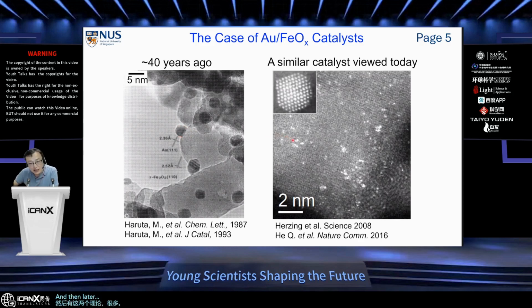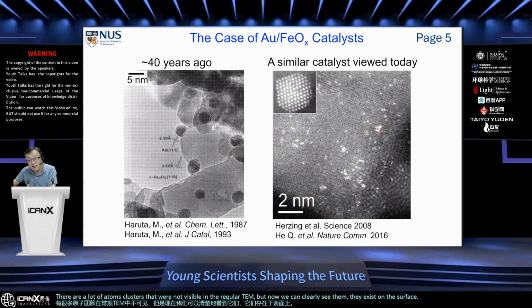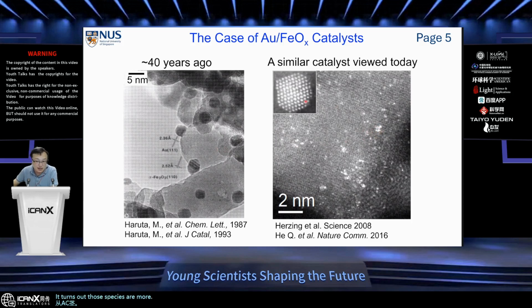And then later, around the late 2000s, when the aberration-corrected STEM became more popular, we studied the same catalyst using a different microscope. We found that in addition to nanoparticles, there are a lot of atomic clusters that were not visible in the regular TEM, but now we can clearly see them on the support from the AC STEM. It turns out those species are more active than the nanoparticles. They are predominantly responsible for the performance of this catalyst. So this is a classic example of how the best of our characterization capability really determines the best of our materials knowledge.